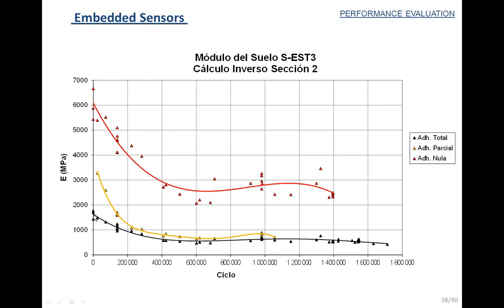And here you can see in black color the original back calculation assuming full bonding. Then in red color you can see the back calculation assuming no bonding. So the red points would be assuming that there is full slippery between asphalt and cement treated layer. And then in yellow you can see the results of the back calculation introducing partial bonding. Basically we saw that at the beginning of the test, the original back calculation was underestimating the modulus, but then as soon as the test started to develop, the situation was similar to the full bonding situation. So this was an interesting result that we obtained.